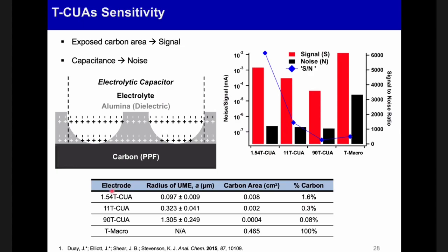We've tried this fabrication with various different sizes of polystyrene spheres. These numbers are just representing the diameters. And T macro is just plain pyrolyzed photoresist, like a carbon electrode. If we look at the radius and the carbon areas, obviously here we have 100% carbon area, and here with the 1.5, we have the highest percentage of carbon area. But the introduction of this aluminum oxide layer acts as a dielectric. So any charging you get from double layer capacitance from just water sitting on the carbon electrode surface is greatly diminished by the presence of this aluminum oxide layer, which organizes the charge.